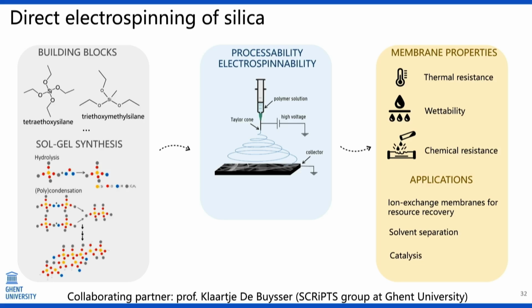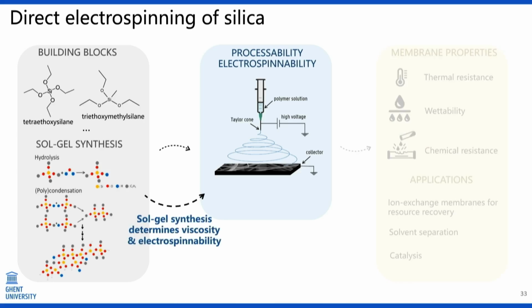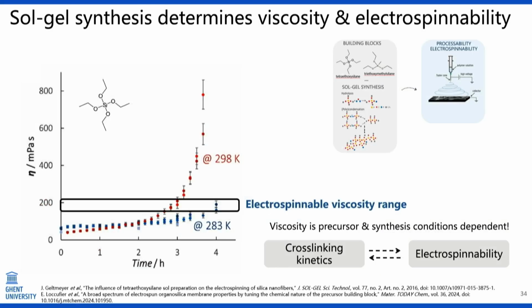The most common one is TEOS, shown here, and then through sol-gel synthesis, we have a range of hydrolysis and condensation steps, and we form a network. If we form the correct network, we can spin that network and then tune different properties. Of course, to be able to spin it, the sol-gel synthesis will determine the rheological behavior and thus the electrospinnability. In our early work, we already showed that we do have an electrospinnable region, but the range is very narrow and is moreover dependent on the type of precursor. If you change from TEOS to another precursor, that range is different, and synthesis conditions dependent, making it a very difficult platform with a lot of trial and error.